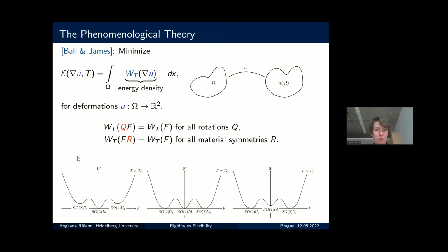So it should be such that at temperatures above the transformation temperature, the austenite phase is favored, so the gradient wants to be in the SO2 orbit of the identity. At temperatures below the critical temperature, the two variants of martensite should be favored. The austenite is still a local minimum, but not a global minimum of this energy density. So you want to sit here or here. And at the critical temperature, austenite and martensite should be energetically equivalent. So you have three, in this setting, SO2 orbits of minima really that are present.